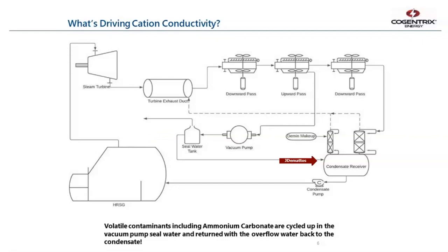Almost all that cation activity that you're seeing is a result of the seal water recycling back to the condensate receiver. We've done trials cutting off that seal water recycle for a short period of time, pumping it into a tote instead, and the cation conductivity around the process goes right back down to normal when we do that. So I'm assuming some of that high cation conductivity could be what was causing some of the damage previously. But that's just the way it is, and we're trying to learn how to deal with it.